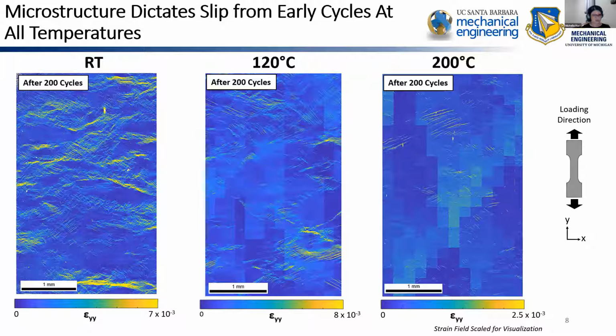Does that make sense? Well, with the lower yield strength, I would expect that for the same kind of force or stress dominated loading, you would actually have more strain. So I understand that it makes it more homogeneous, but why would it actually lead to a lower strain?